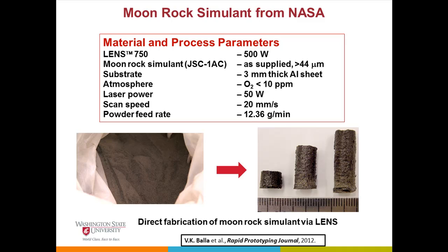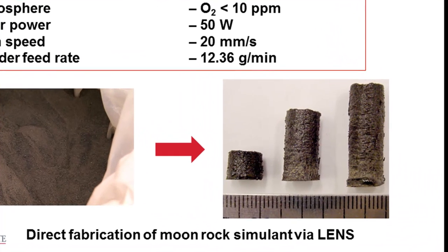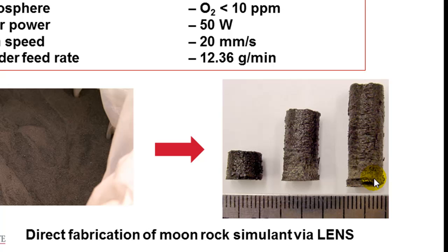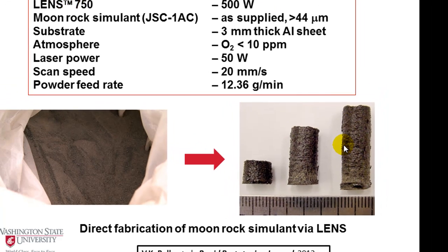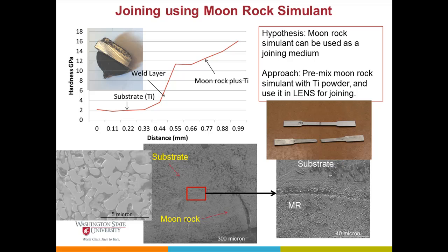But if you want to make even a brick or things like that, you're not talking about laser sintering, you're talking mold casting. We are basically taking the moon rock regolith, melting it and casting it using laser power, building these parts layer by layer. Again, these are not large huge structures, but it shows it's possible. This particular composition had a lot of silica, so you can see the glassy phase, but it's possible if we want to do that.